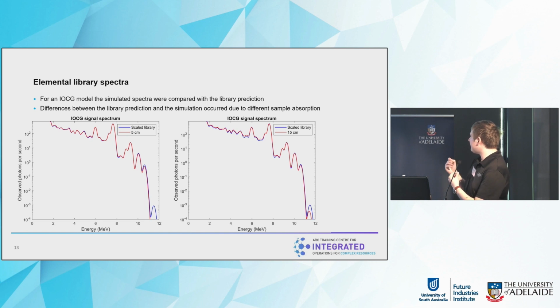However, we can begin to see some variation between the library prediction and the compound material measurement for 15 centimeter. This is due to the fact that relatively small samples are used, so for a thicker test case, there's differing levels of neutron absorption, which begins to result in differences between the elemental library spectra and the actual measured spectrum. And accounting for this could help improve the analysis.